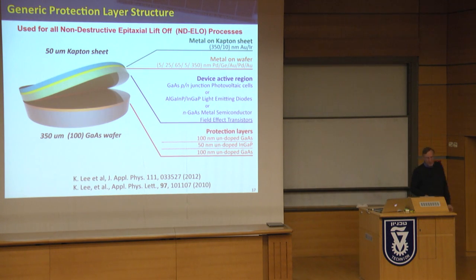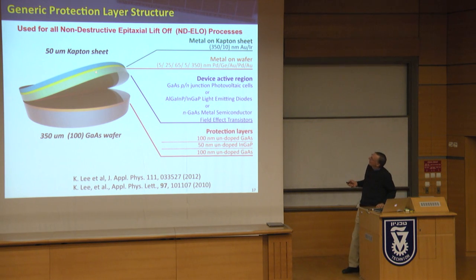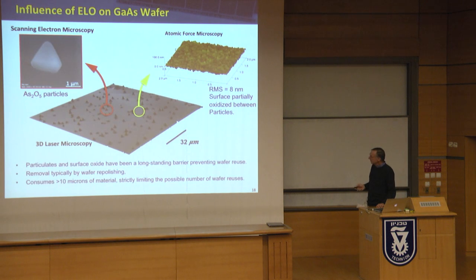Okay, so let me go back to this non-destructive process. This is the generic wafer. You can see there's a gold bond to the Kapton that we use for the plastic substrate. This red line is the sacrificial layer. We just basically use HF to etch that out, and then we have these protection layers.